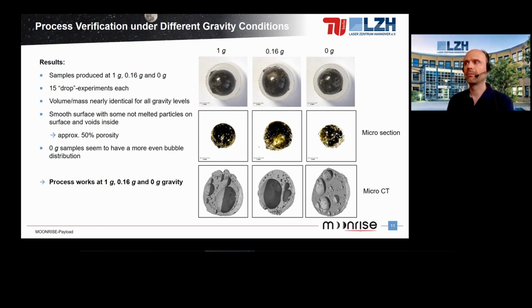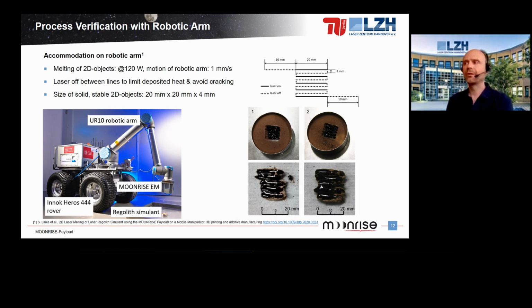You have a smooth surface with some not melted particles on the bottom. And if you do a microsection or a micro CT, you can see there are bubbles inside. You have about 50% porosity. If you look at the 0G samples in the micro CT, the bubble distribution seems to be a little bit more even, but the take-home message is that the process works at 1G and lunar gravitation and even at 0 gravitation.